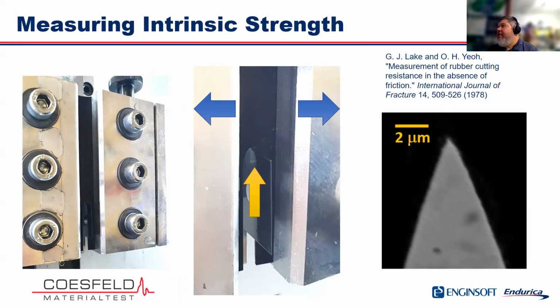The method that we use is a method that was originally proposed by Graham Lake and O. H. Yeoh, who at the time were working at the MRPRA in the UK. And they proposed a method that uses a very sharp blade. You use a planar tension test piece. You stretch the rubber, right? The blue arrows are showing the rubber stretching in the horizontal direction. And then once the rubber is stretched, you cut the rubber with a blade.